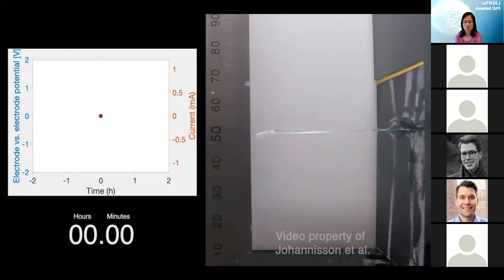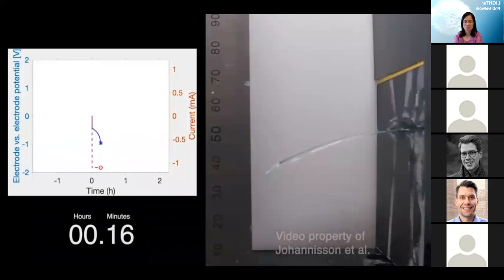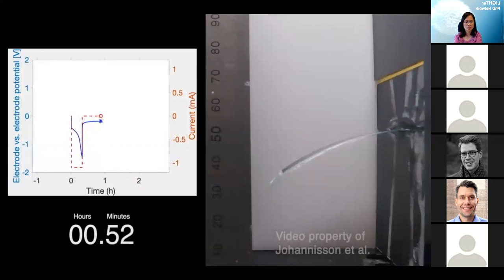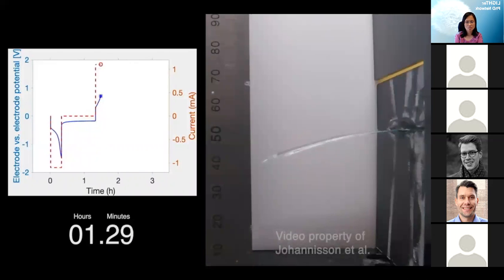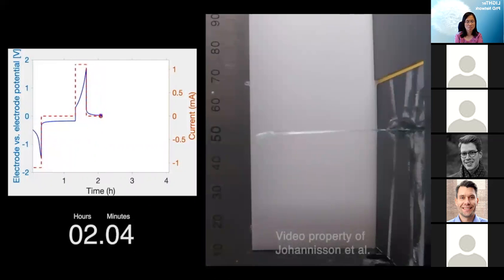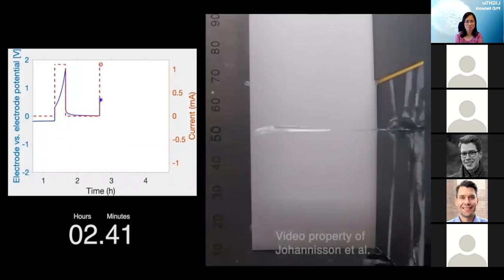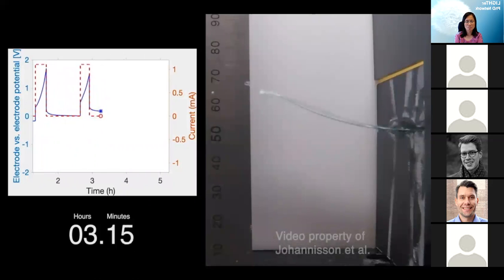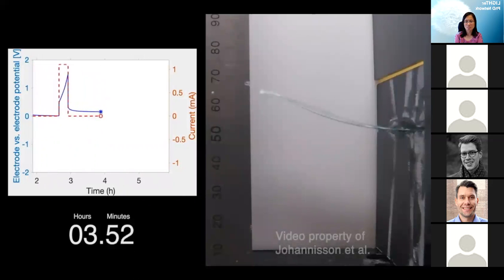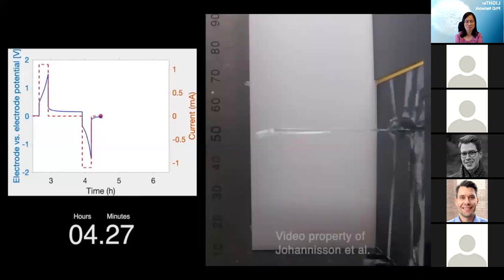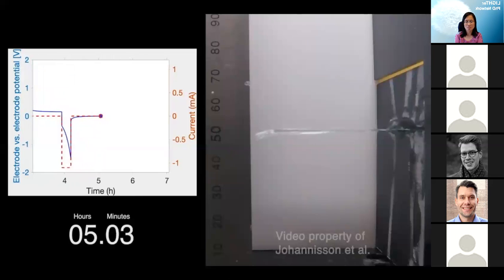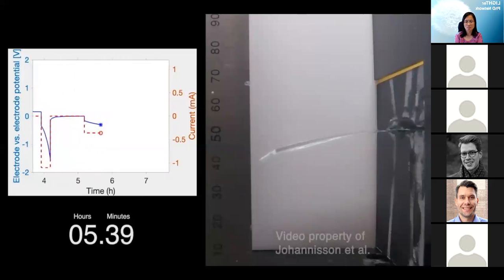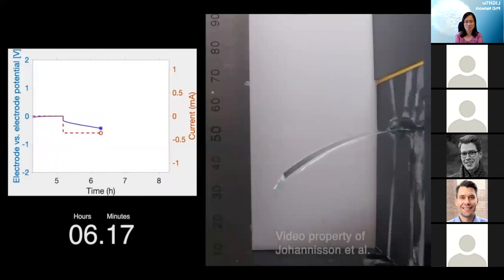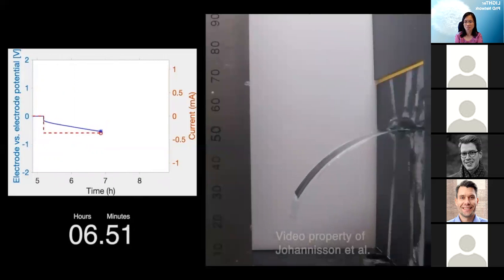A high current is applied, leading to an actuation in about 20 minutes. Next, the current is reversed, then stopped after a further 20 minutes to take it back to center. The reverse current is again applied, this time leading to a bending upwards, before one more step of current brings it back to center. This time, the current is lower, leading to a slower but larger deformation.